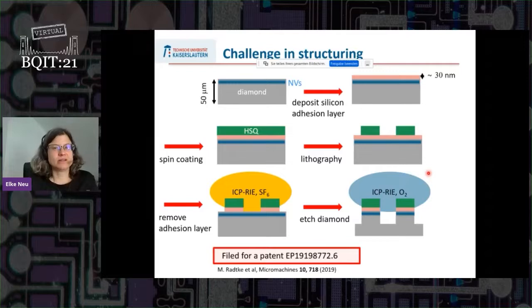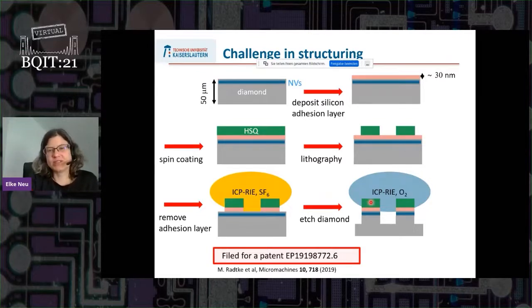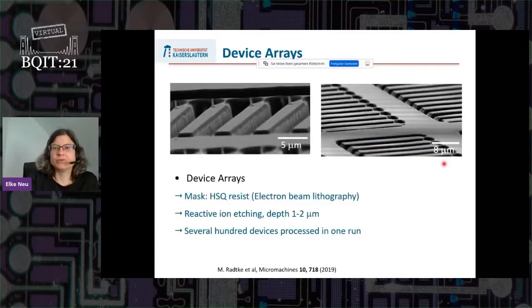I don't want to go into details of the nanofabrication process, just to let you know that it is not so straightforward, because diamond is not a straightforward material. So you need very sophisticated etching plasmas. You need to make sure that everything you put on here adheres to the diamond. And this has cost us some time, but we now have a working process, and we can produce larger arrays of these devices, several hundreds of them. You see here the pillar, you see the mounting structure, and maybe it's best to see here. This is just connected with a weak link to the rest of the sample, because we now want to pick one of these tips and bring it into our AFM to do the measurements.